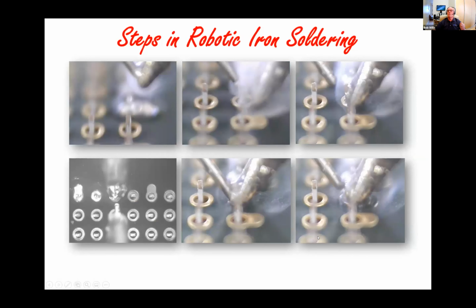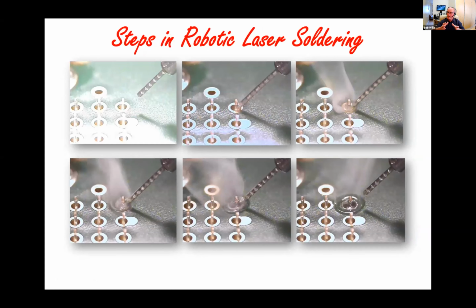The fundamentals of soldering don't really change. So when you look at iron soldering, the steps are pretty much a mimic of what you do with a soldering iron in the normal manufacturing environment, although it's automated. With laser soldering, it's slightly different in that we have solder wire that we feed to the joint, but we use the laser to preheat the board, to preheat the solder as it's coming to the joint, and then reflow the solder as we add solder volume to fill the plated through hole.